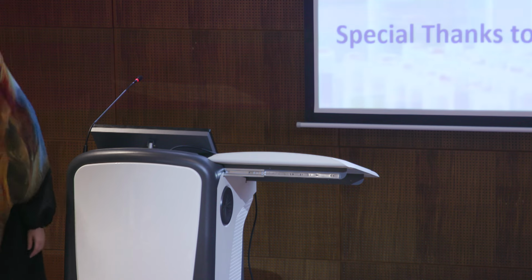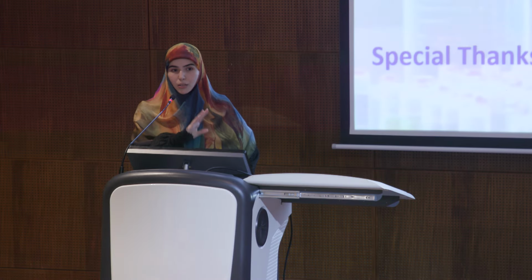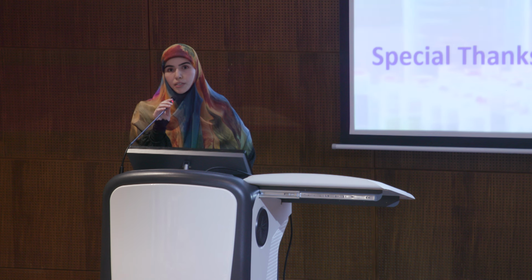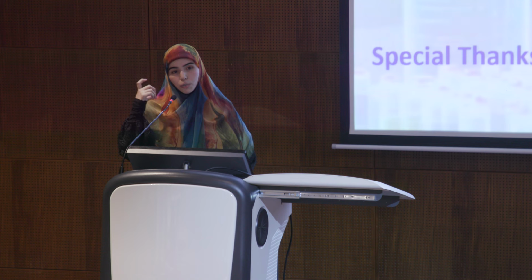Hello. So how much time does it need for the antibiotics to be fully removed, and what's the benchmark of how much antibiotics are left in the solution for it to be safe? I'm going to compare our results with the published work we did already using the nano-sized TiO2, the photocatalyst, rather than immobilizing it. In the first published work, we reached 100% removal in just 80 minutes. Okay, 80 minutes, so it was fully removed. How much solution did you put inside? The concentration was 200 milligrams of tetracycline in the solution. The volume was around 300 milliliters.